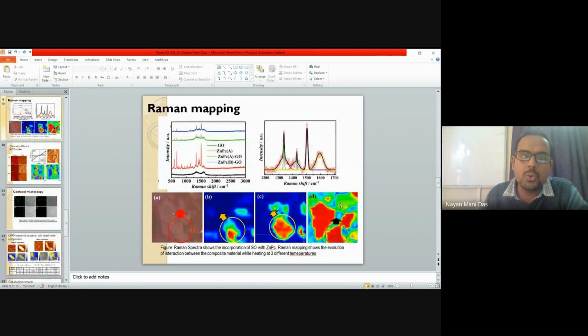So this is also shown here, the Raman graph and the Raman mapping. Here we have convoluted the Raman graph from this red graph. This is the heated graph, actually the composite which was heated to 580. It is shown here that there are two peaks at around 1300. This peak and this peak are for the graphene oxide, and the other peaks are for the phthalocyanine.